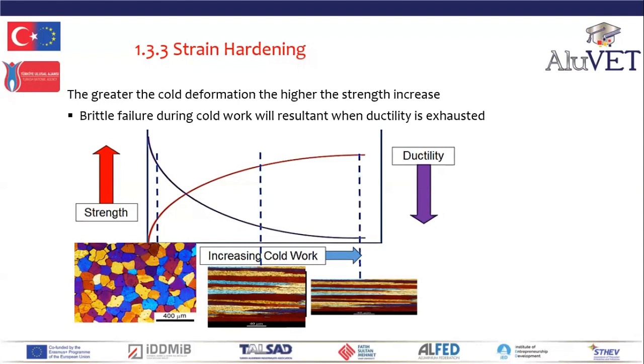And as the cold work increases, maximum strength will be developed with the maximum deformation. So as we've severely cold worked the grains, as you can see in the slide, we've developed extremely high tensile strength. However, the corresponding ductility is becoming exhausted to zero. And if we carry on working, we will end up with brittle failures because there is no ductility left. So there's a balancing act between strength and ductility of cold worked metals. The limiting factor of the maximum strength we can develop is that ductility can be reduced to the point of brittle failure.